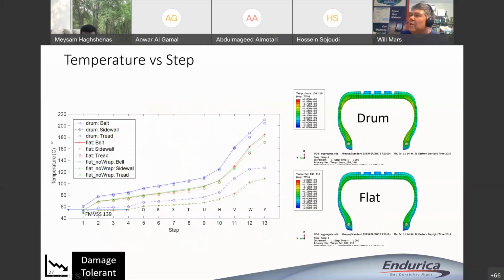So this is a picture of the calculated temperature as a function of the step in the test. You get the standing wave right here at about step 10 is where it starts, and then you can see the temperature just shoots way up in these tests. These are contour plots showing the temperature. Here we're comparing doing the test on a curved drum versus on a flat road. The drum is more severe, and we can predict that with our models.